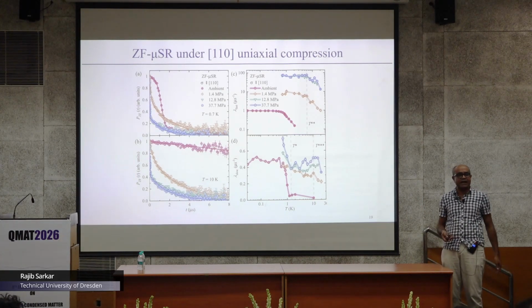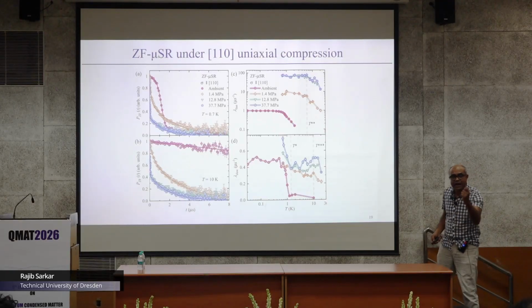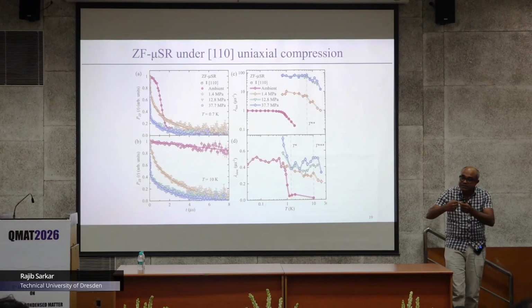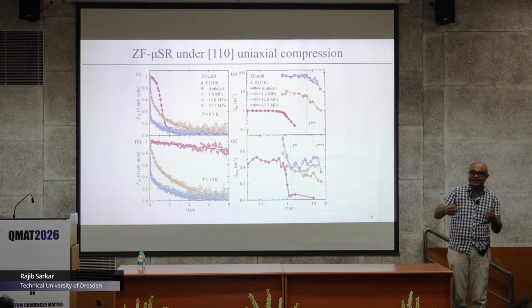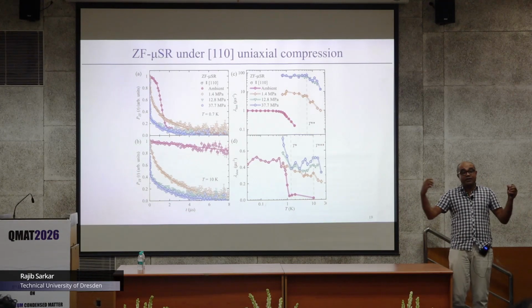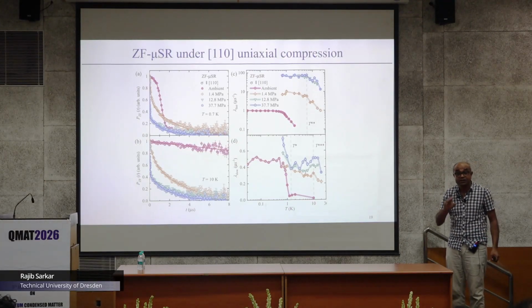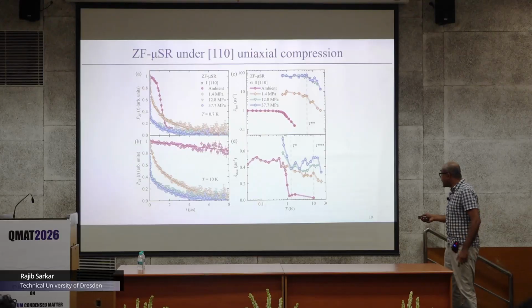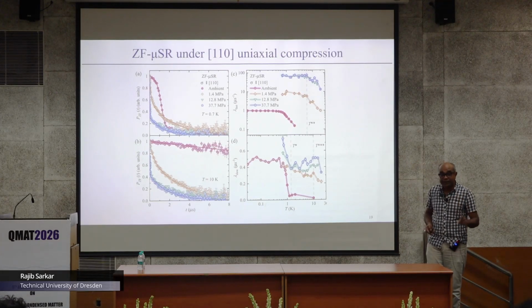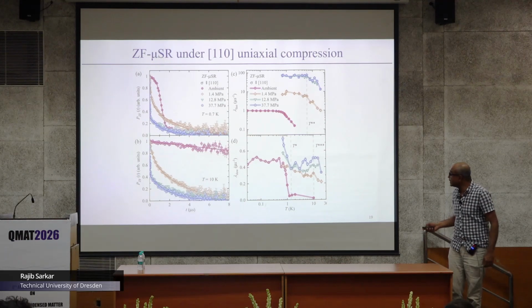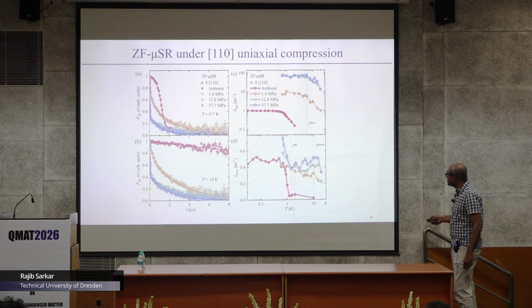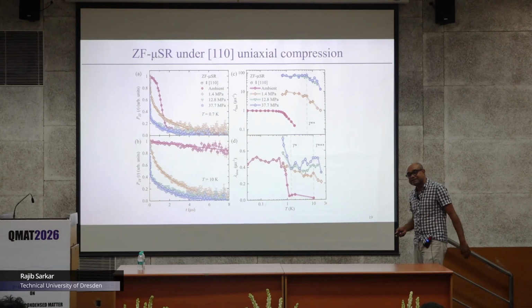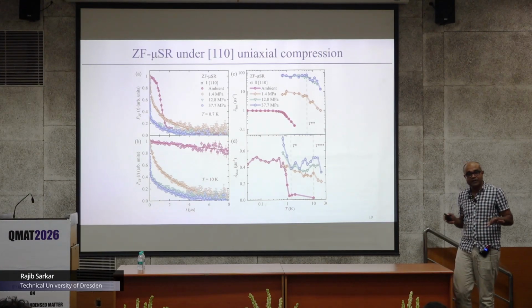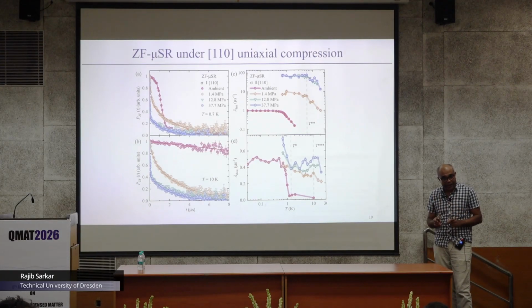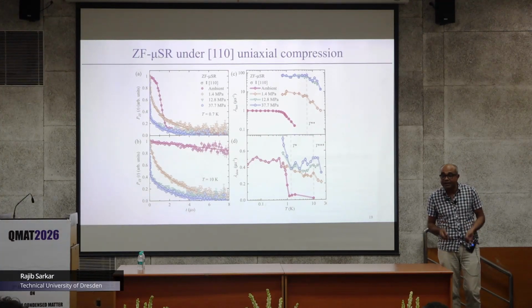That means you have a very fast dynamics, very fast decay of your muon relaxation. And how is it possible? This is only possible when your system possesses a high degree of static correlation. Okay? We cannot tell this is completely static order, then you would have probably an oscillation or something like that. This is a high degree of static correlation. And the second part, we also need a slow dynamics. Yeah, we also need a slow component to fit the things. And there you see that, okay, at ambient condition, more or less, our relaxation rate increases and then basically becomes constant. Okay, so the take home message is very simple, that by applying uniaxial strain or uniaxial pressure, we are definitely influencing our relaxation channel dramatically.